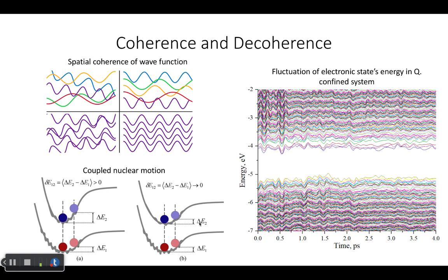But why should we choose it? It's probably that it should not have, because again, don't forget it's a semiconductor, right? So all the states nearby, it's not just LUMO. It's LUMO plus 1, LUMO plus 2, and so on. They're all nearly degenerate bands with pretty much the same character. So even if they cross or flip, their character probably changes, but insignificantly.